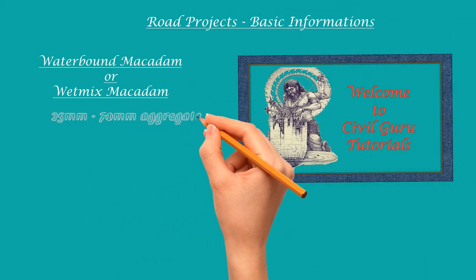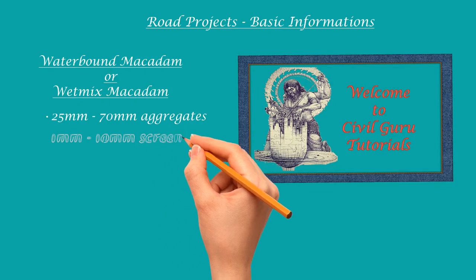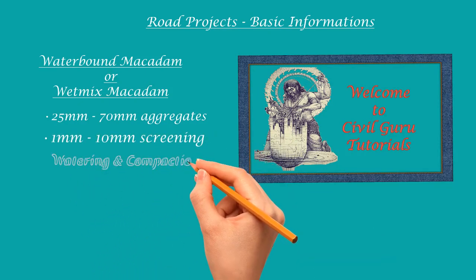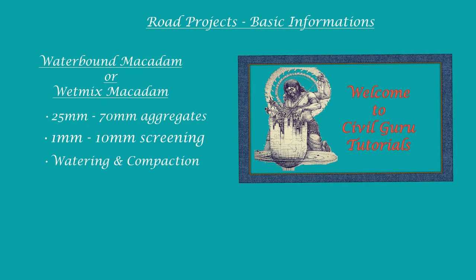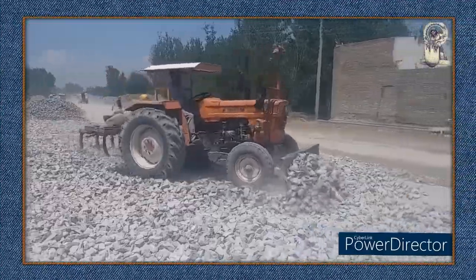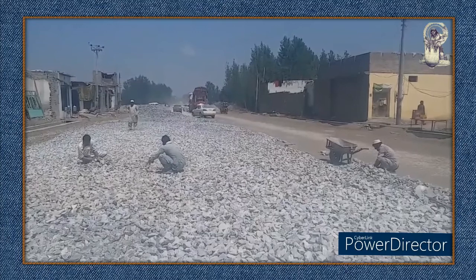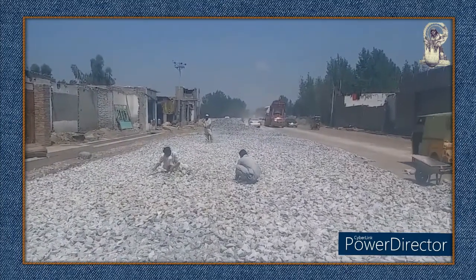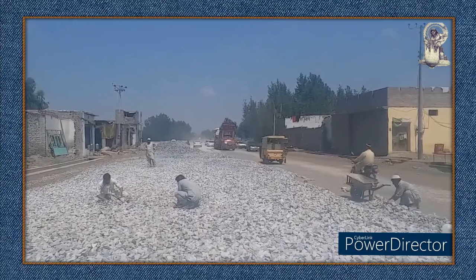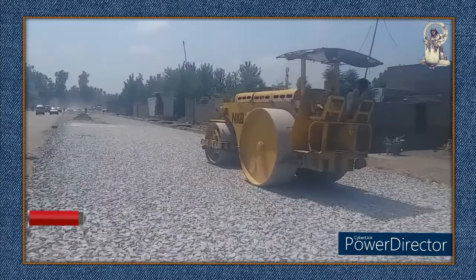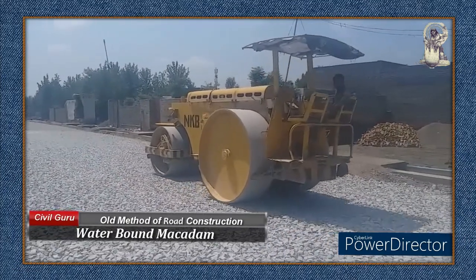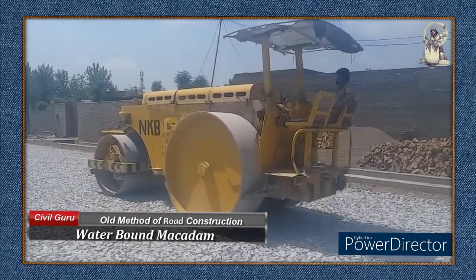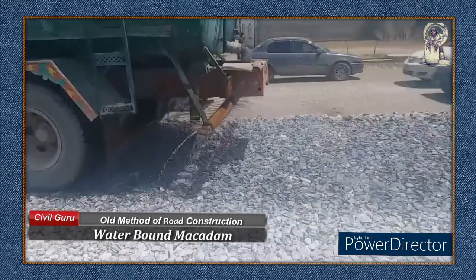Now, let us see about waterbound macadam and wet mix macadam. Waterbound macadam is the oldest method of road construction. This layer falls in between the subgrade and bituminous macadam. Normally it is laid in two layers, each layer consisting of 7.5 cm to 12.5 cm based on the design of that particular road, which is calculated as per the traffic and types of vehicles moving on that road. Waterbound macadam is executed by spreading 25 to 70 mm aggregates on the subgrade, manually or mechanically, and then compacting it with a heavy roller.